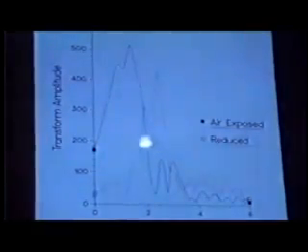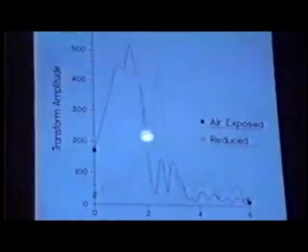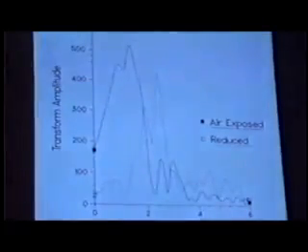However, we have analyzed this data further, and our tentative conclusion now is that this side lobe is noise in the data and is not indicative of ruthenium-oxygen coordination. Now, EXAFS did not show ruthenium-oxygen coordination for the highly dispersed catalyst.